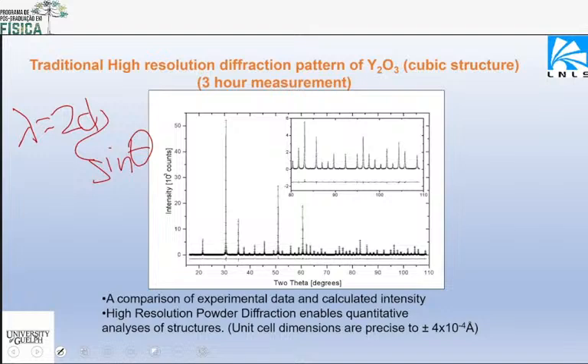It's a very nice sample. And it was really measured to be able to show that the apparatus worked really well, and it did. And you could see in the inset a difference between the calculation and the measurement. And the difference is this tiny little glitch there. So what I'm getting at here is that a calculated diffraction pattern from a model is going to match the X-ray data really well, and vice versa. So it means that the X-ray data is going to really tell you in a reliable way the structure of your sample. Okay, let's keep on going.